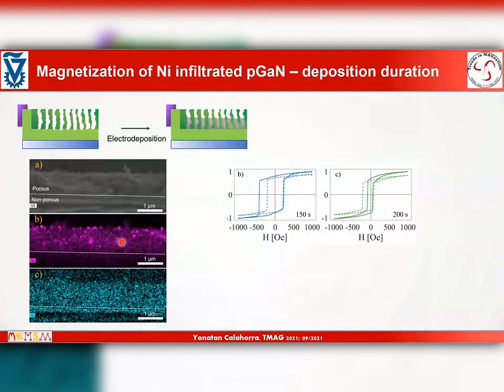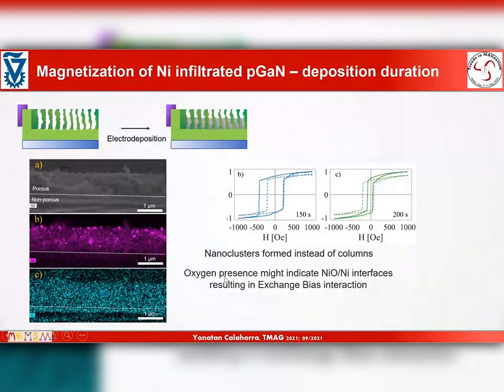And we actually see in EDS that we have nickel embedded inside the porous layer, but not as these columns that we thought we would get, but more in these clusters or nanoparticles of nickel. We also see more oxide in this area. And what we actually think is happening here is that we get these nanoclusters. These nanoclusters get slightly oxidized, and then the interaction between the nickel oxide and nickel could present as an exchange-bias interaction and cause some of these peculiarities in the coercivity.